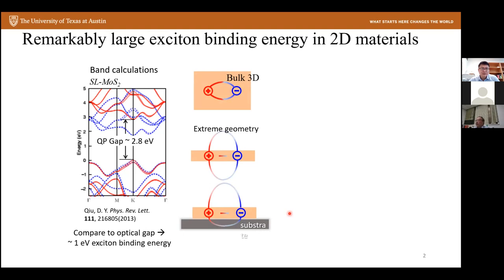Now, there's a very easy explanation for this. If you think about a bulk material, an exciton is like one hole and one electron bound together. And for the binding energy, you can just think about using the hydrogenic model. You have all learned that the dielectric environment really cuts down this energy scale quite a lot. And so for the bulk 3D exciton, the binding energy scale is roughly a few meV at most, just 1 to 5 meV.